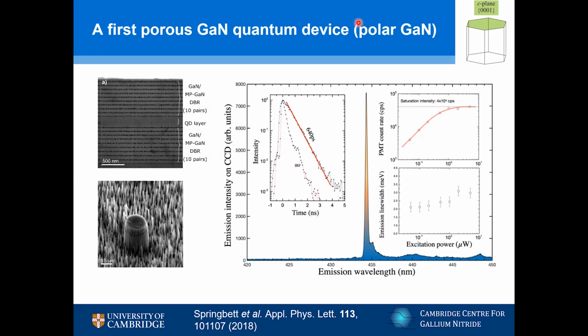I have another question, and perhaps I am not fully understanding how this is working, so forgive me if that's the case, but it seems to me that a certain type of defect, the dislocation, is how you're able to form the porosification of the layers. Is that right? Absolutely. And so that allows you to form these DBR mirrors. Mm-hmm. But in general, intuitively, I would think that you'd want your defect density to be low. So does that mean that there's some kind of trade-off when you're thinking about making these cavity style devices, where you need a certain number of defects in order to form the mirror layers, but you maybe ideally want that defect density to be lower for other reasons?